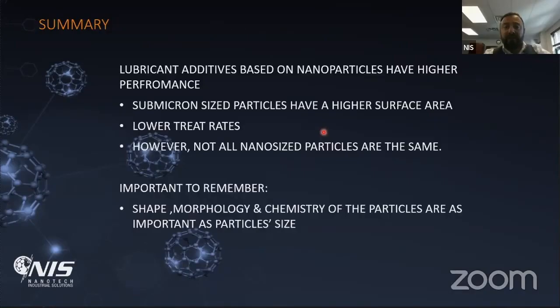So as a summary, I would like to say that lubricant additives based on nanoparticles have higher performance in general. Also, you need to really pay attention to size, shape, and treat rate, and not all nano-sized particles are the same. Very different mechanism in many cases, and it works very differently. So you need to apply this material to the right application and consider many points that I mentioned before, stability, of course, and compatibility with the other components in the lubricant.